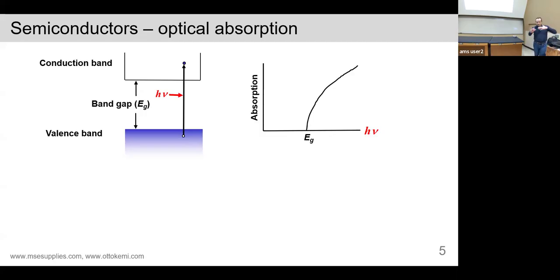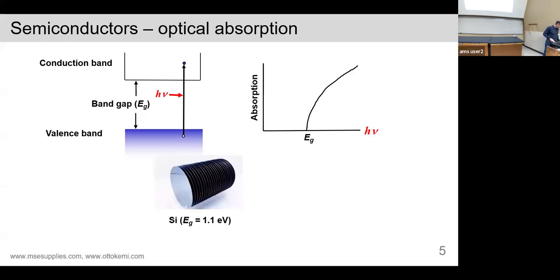And so you can see that as absorption versus photon energy. You'll suddenly get a large absorption above the band gap energy. But below the band gap energy for a pure semiconductor, it's transparent. So if you see a crystal, it's transparent, you at least know that its band gap must be greater than 3 or 4 eV. So silicon has a band gap of